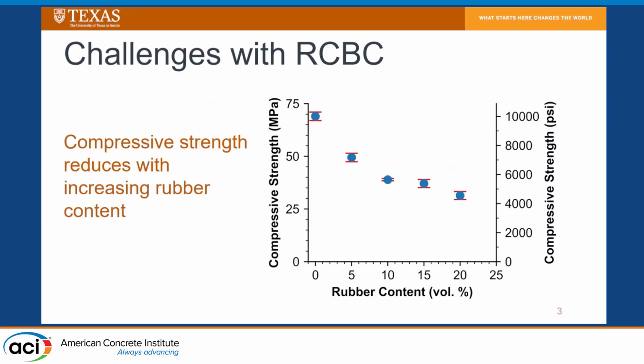However, when we do look at adding these crumb rubber tires into our concrete, one of the major challenges is that you're going to have a significant reduction in your compressive strength. Over here you can see a figure showing that compared to a concrete or mortar sample that does not have any rubber, when you start replacing some of your natural aggregates with the rubber, you're going to have this decrease in strength. And it's going to increase as you increase your rubber content.